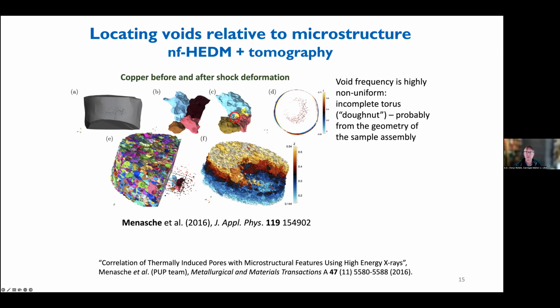And thanks to being able to repeat the mapping and register the voids and the second mapping back onto the original experiment, we were able to correlate where those voids occurred in relation to the microstructure. So the motivation for this experiment was, what is the link between the microstructure and voiding under these conditions? Is there a microstructural feature that is predictive of those voids? And I remind you that the more or less classical idea is you just have to look for the places in the material where you have the smallest pressure, the most negative pressure, or the largest tensile traction, if you like, across some surface, or across some cross section. And that's been a fairly typical thing to use in damage modeling. And in case you're curious, the answer is it didn't work.